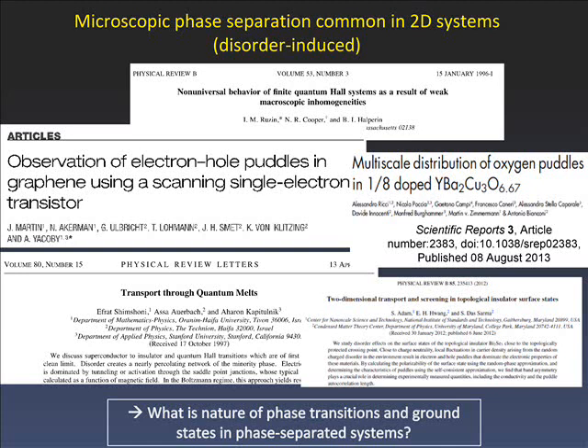The idea of phase separation itself is relevant to many sorts of low-dimensional systems. In general, if you take a 2D film — whether it's a topological insulator or graphene — and put it on a substrate, there'll be disorder. That disorder tends to make the system phase-separate into some sort of inhomogeneous system. This is seen in TIs, in high-Tc, and in graphene. It's still not well understood what is the nature of phase transitions in these sort of inhomogeneous phase-separated systems.